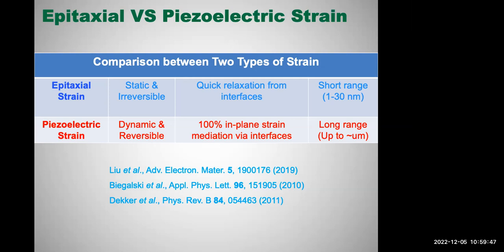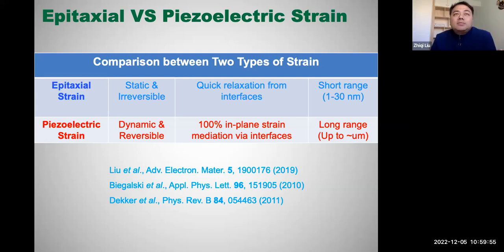Okay, so actually both materials could have advantages and also disadvantages. For non-collinear antiferromagnets, because they have a very strong magnetoelectronic effect, they could be turned on and turned off by external magnetic fields because of very small, tiny canted magnetic moments. It's around milli-μB per atom, about three orders of magnitude smaller than the ferromagnetic moment. For example, for iron, we have 2.2 μB per iron. For non-collinear antiferromagnets, you can control their spin structure by external magnetic fields, and then you can also use their anomalous Hall resistance to realize memory devices.